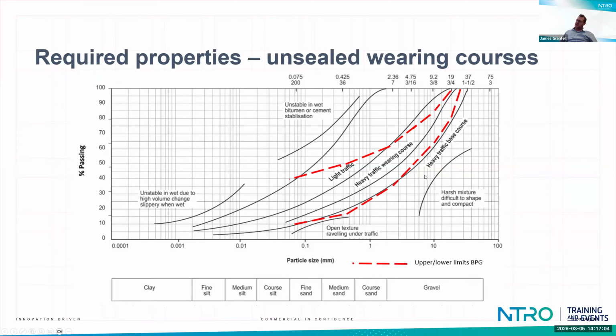As we go on the coarser side, moving to the bottom right of the graph, we get more coarse materials, so they will be working better under heavier loads. And as we move up towards the top left, we have finer gradations, so tending to be better for lighter traffic conditions, or in wearing course conditions where we can get a tighter wearing course, a smoother surface to allow our vehicles to run on. All of this, I guess, is just setting the scene of what we're trying to do. And generally, if we were looking at road building materials, we'd be aiming to be somewhere in the middle of our grading envelope to get the desired performance. And obviously, depending on whether we were talking about a base course or a heavy traffic wearing course or a light traffic wearing course, we could be at different levels within our grading envelope.